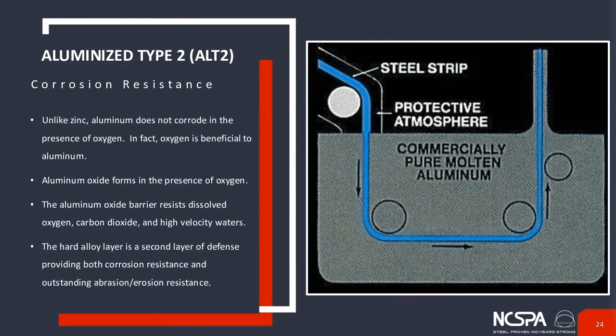One of the main things that you need to understand about aluminized steel and what makes it different from galvanizing, and Mike will talk about it in more depth as we go on, is that, as that first bullet said, unlike galvanizing or zinc, aluminum doesn't corrode in the presence of oxygen. That's a big difference. In fact, oxygen causes an aluminum oxide film to form on the exterior of the